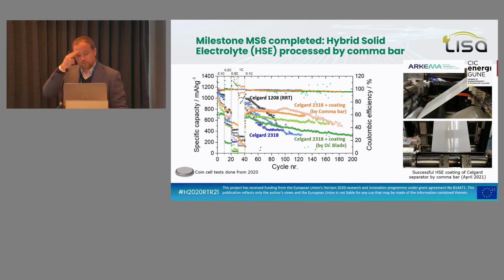This is a result on the hybrid solid electrolyte coating by Comabar on a polyethylene separator. This is a ceramic lithium conductive material that is embedded in a polymeric matrix. Here we reach 7 micra of thickness on top of the separator. We have been working a lot. We met a lot of issues making the composite stable because the ceramic surface is reacting with the polymer and with the humidity, no? So it was not easy to make it stable. And also it's not easy to make it at 7 micra because the particles in general are bigger, 20 micra or more. So you have to pre-treat and post-treat your material to reach this result.